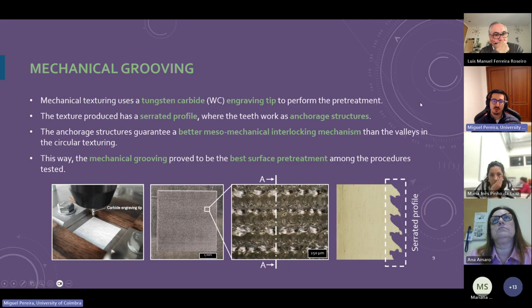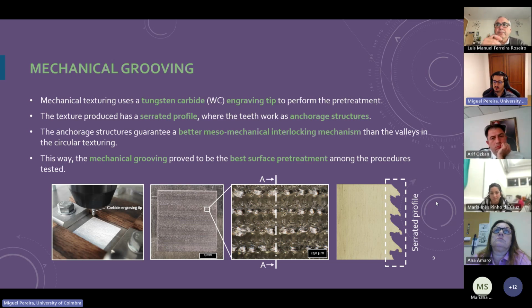Finally, we tested the mechanical grooving procedure, which uses a tungsten carbide engraving tip to perform the treatment. It results in the shown multilinear pattern. And when we analyze the cross-section, which is here indicated on the right image, we see a serrated profile, which is composed of anchorage structures, as we can call teeth. So these anchorage structures warranty a better mesomechanical interlocking mechanism than the previous procedure. This type of mechanical grooving surface pretreatment resulted in the best surface pretreatment and in the best mechanical performance.